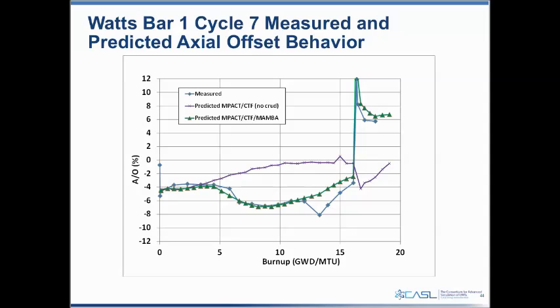And the next one shows the axial offset behavior. The prediction there, the purple curve with X's in it, is really the standard MPACT/CTF prediction without modeling crud. You can see early in the cycle, axial offset is predicted pretty well, consistent with measurement. But then in the middle of the cycle, the measured values were more negative because the core was experiencing CIPS.